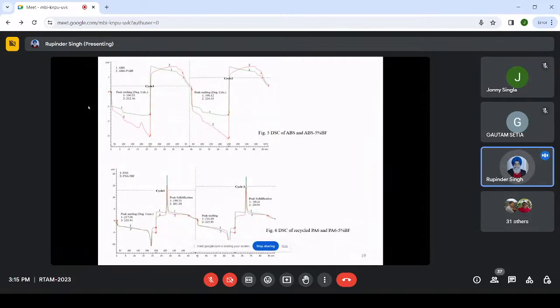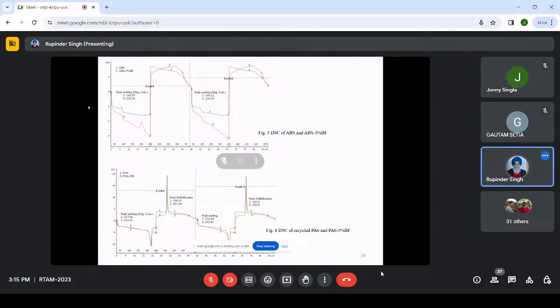Right. So to understand this, take one example. Suppose I go to the market and purchase two buckets, same color, same dimension, everything same. One I keep on my rooftop, and another bucket is in my bathroom. What we will observe is that the bucket on the rooftop may develop cracks soon, maybe in a month or so, whereas the bucket in the bathroom does not, because of low exposure. There is excessive heating during the daytime, and in some places the temperature variation is very high, so at night there can be extra cooling.